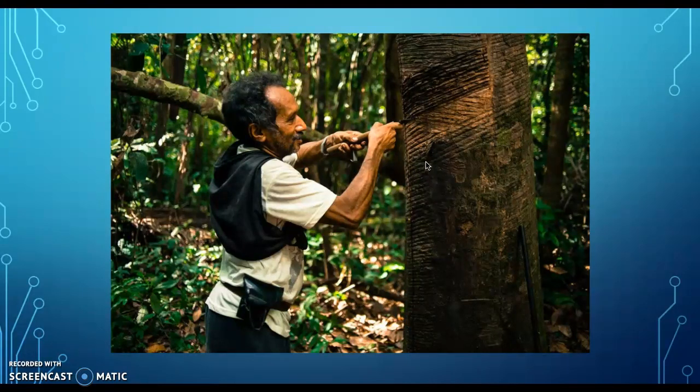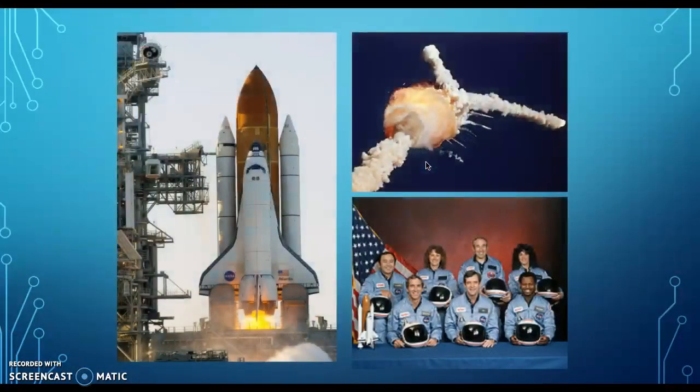Rubber was also used in an O-ring in the Space Shuttle Challenger for NASA without them considering the properties, resulting in rubber getting too cold while up in space and not returning to its proper shape, which caused an explosion due to a gas leak, losing the lives of 7 astronauts.